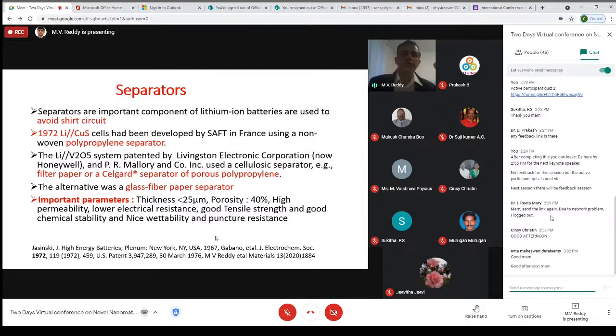Separators are very important components of batteries, again to avoid short circuit. The important parameters we consider are thickness less than 25 micrometers, porosity, high permeability, electrical resistance, and good tensile strength. These are very important points if you want to design separators.